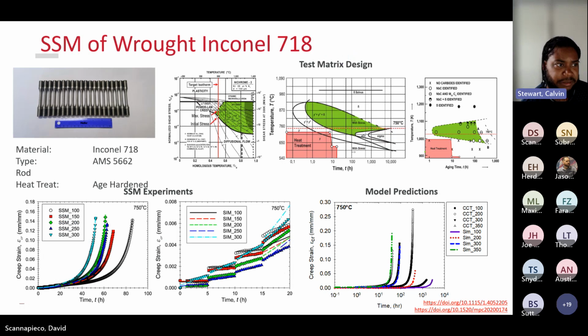So this is an example. This is a paper that we published in ASTM's Materials Performance and Characterization journal, where we studied some wrought Inconel 718. We age hardened it. We found the mechanism maps and precipitation maps for it, and we targeted certain regions to design our test matrix. Then we went and performed some of these SSM tests, dynamically increasing load over a period of time, really short-term tests, less than 100 hours. And then using our well-posed model, we were able to predict conventional creep curves out to over 1,000 hours. I think it was actually out to about 4,000 hours is what we were able to predict. So this really saves a ton of time. A number of tests less than 100 hours gets you all the way out to 4,000, compared to conventional creep tests. So this was a really positive result for us.